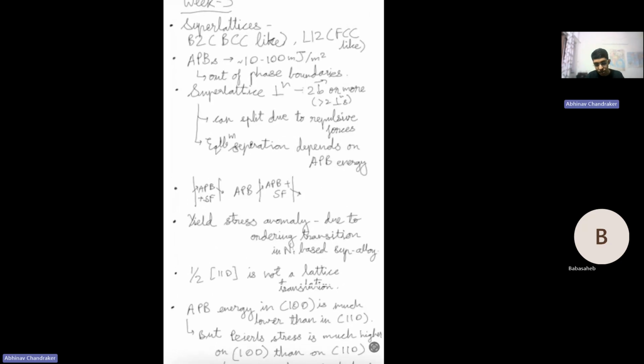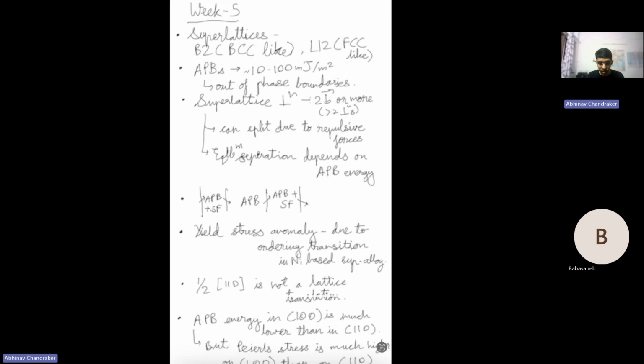Similarly, we have the L12 structure, which is FCC-like, and the most popular or common L12 structured alloy is the nickel-based superalloy, in which the gamma prime phase is L12 ordered, and it helps in improving the high temperature strength of the material. So in these ordered lattices or ordered phases, the dislocations have somewhat different characteristics. In these cases, it's possible that if a single dislocation moves through, it can form antiphase boundaries.